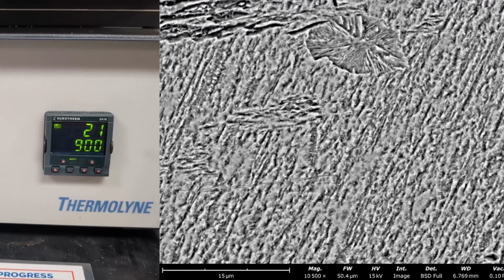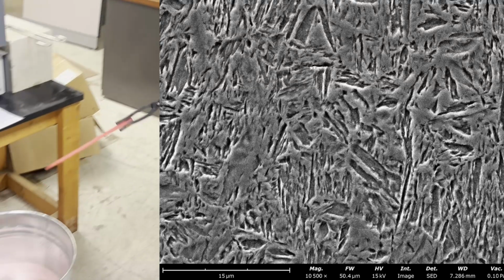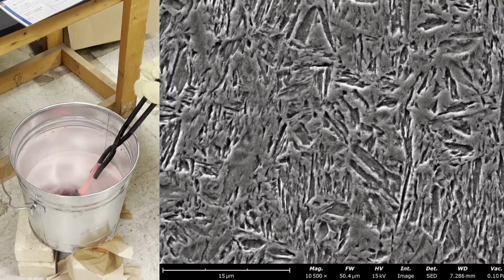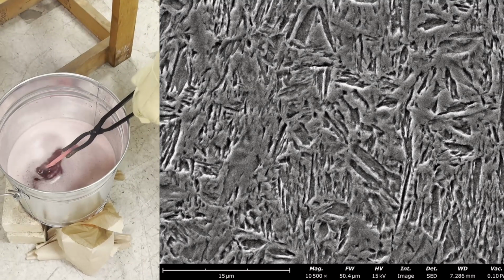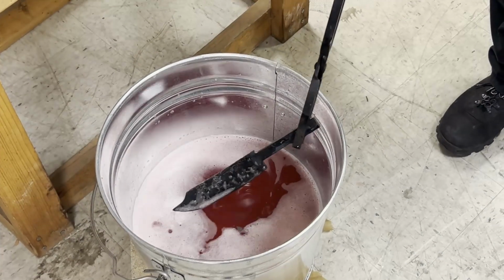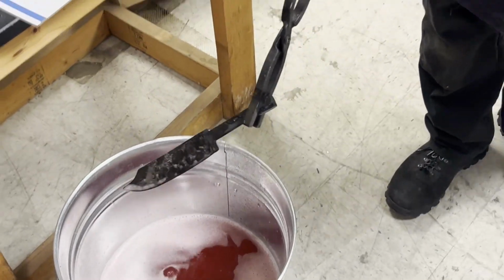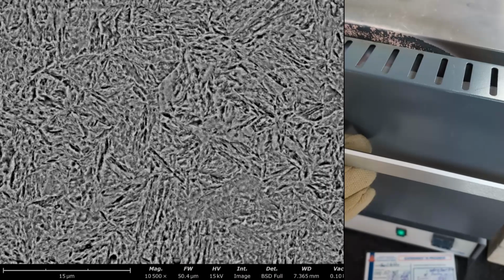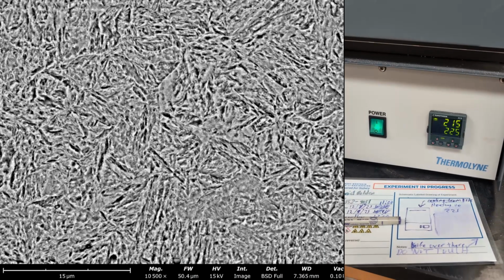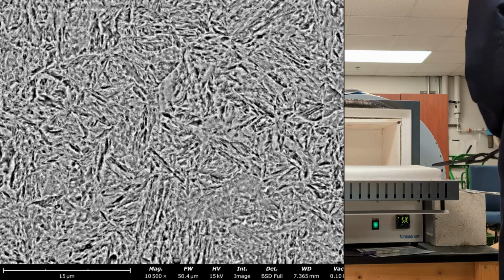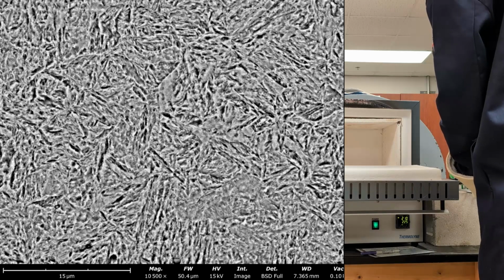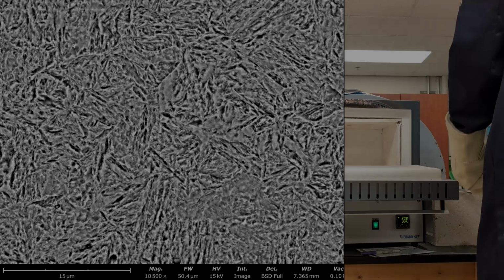We then heated it to 900 degrees Celsius for roughly 90 minutes, followed by a Gatorade quench, cooling the FCC austenite into BCT martensite. This greatly increased hardness at the cost of introducing internal stresses. To resolve this, the blade was tempered at 225 degrees Celsius for 1 hour to produce tempered martensite, leading to a more balanced combination of hardness and toughness suitable for a knife application.